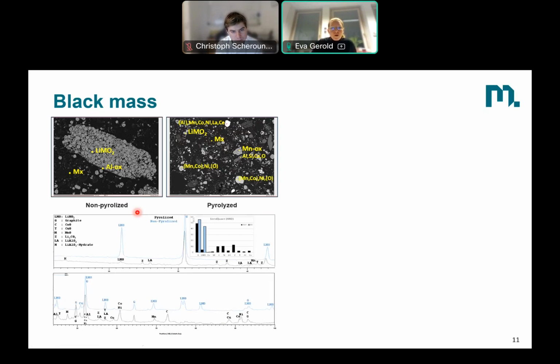So here you can see a non-pyrolyzed black mass. You can still see cathode materials sticking together. And here you can see a pyrolyzed black mass, so a thermally pretreated black mass, which looks completely different, very scattered, and where you also find oxidic but also metallic particles in there. So it's not a defined residual material.